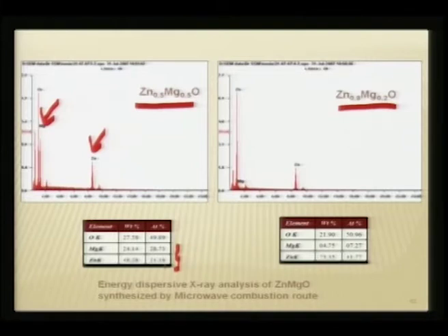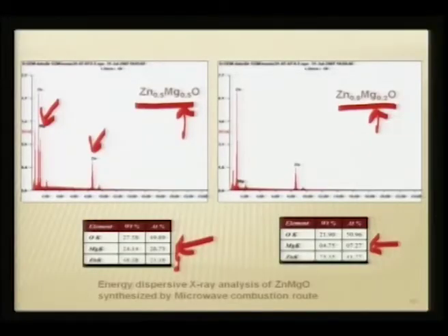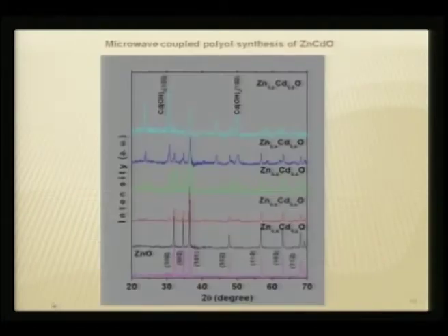If you are thinking of a 20% doping, you can see only 8% is doped. If you go for 50% doping, you see roughly 30% of magnesium is doped. So, there is still an inconclusive issue regarding the relative stoichiometry, but nevertheless we see this is the maximum that we could go: maybe up to 30% of magnesium can be doped outright because of this exothermic process.